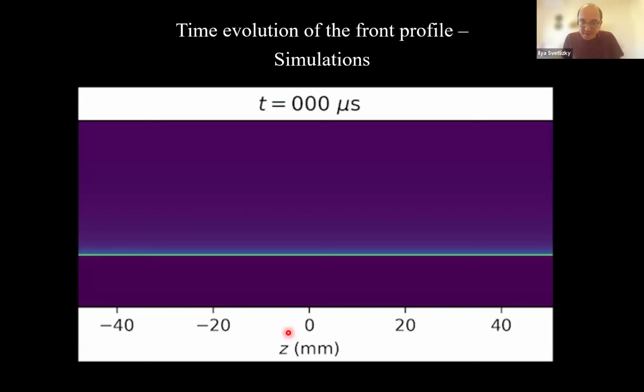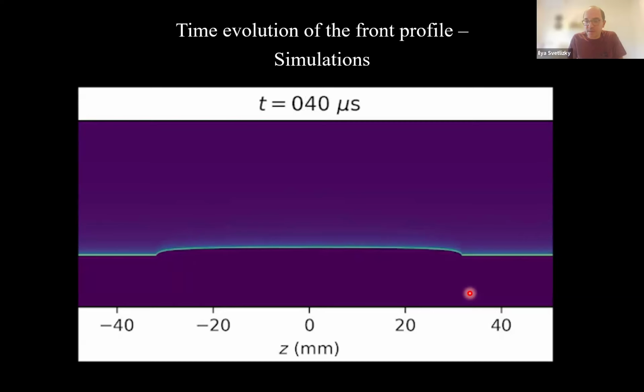So this is a movie of this simulation. The x-axis is along the crack line. This is the crack front. It's a straight line. When I start running the movie, what you see is that the crack is nucleated in the middle. It jumps and starts expanding in a transverse direction. And at this moment, you cannot stop the crack. It's self-sustained. So this looks very promising.